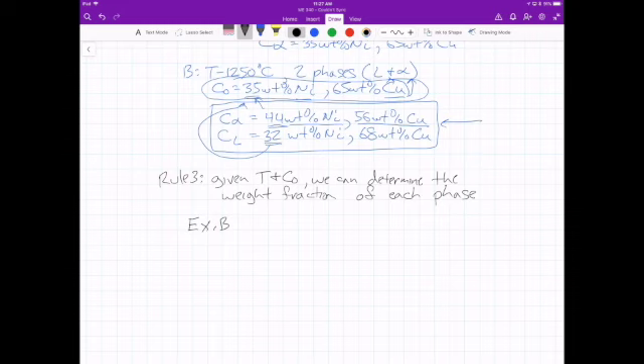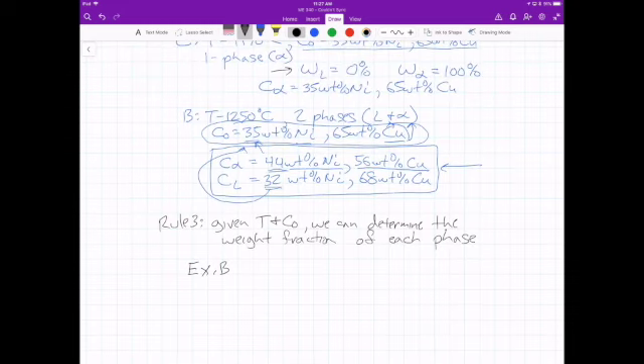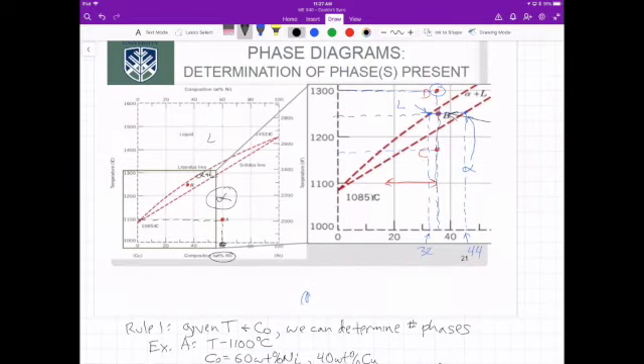For this, we need to use the lever rule that I talked about. So let's look at this line. I'll try to draw it in different colors here. So we have a distance from our point to the liquid phase line. We have a distance from our point to the solid phase line. Let me just draw this off to the side. We have a line that looks something like, got the red, we have our point, and we have the green. Okay, and we have our phase boundaries on each side. This is what we use to calculate weight fraction, and it's the lever rule. Basically, like sum of moments, if you want the liquid side, you use the opposite length. If you want the solid side, you use the other length.